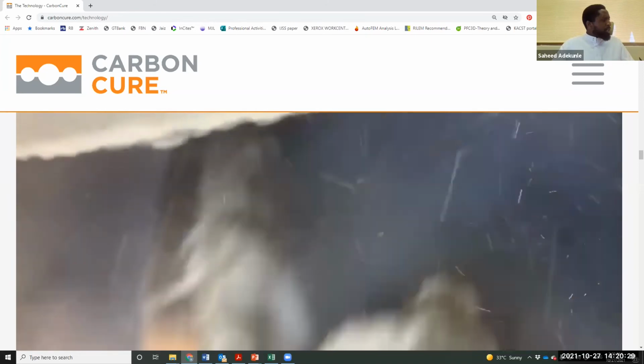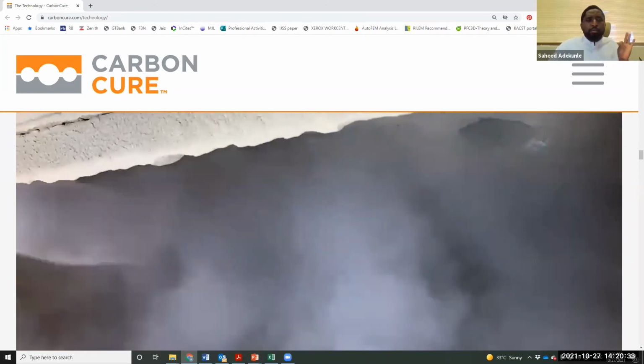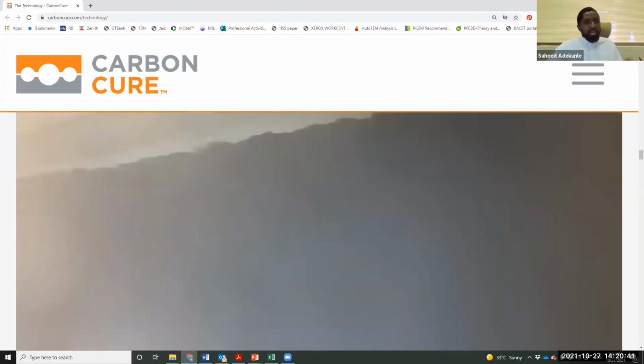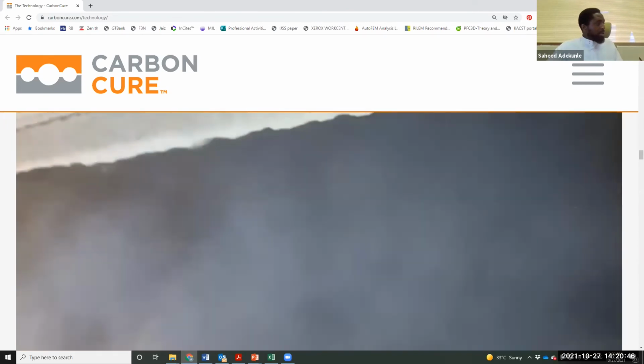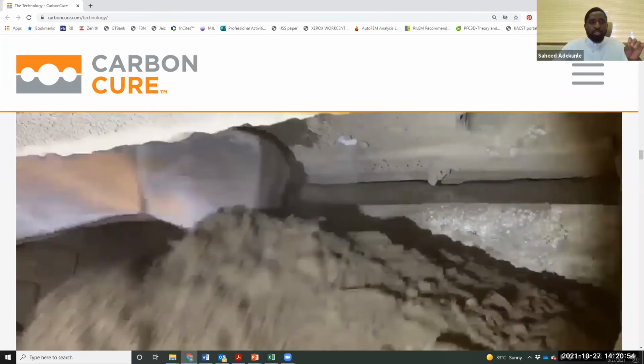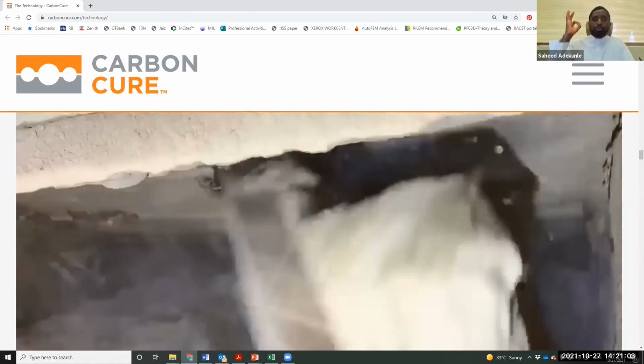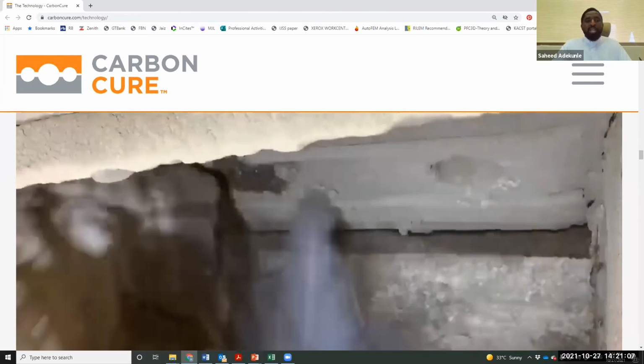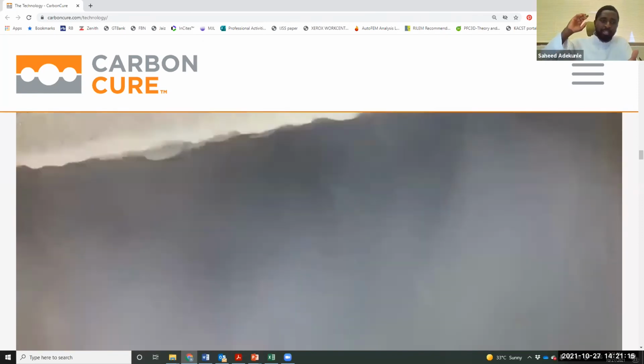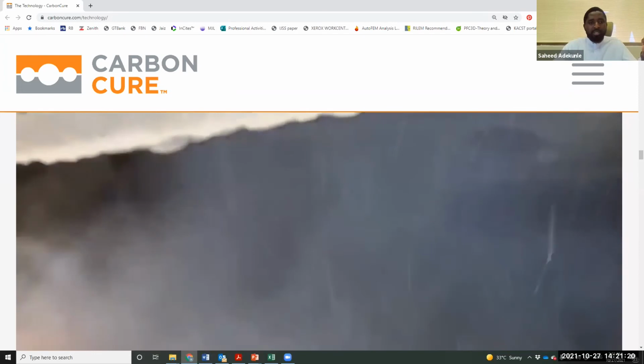Yeah, thank you so much for that question, because again, I'm showing on the screen the technology of CO2 admixing. This is a controlled dosage. As you can see, CO2 is pumped at atmospheric pressure. It's not under pressure. And by the way, in this technology, what you are seeing pumped here is raw captured emission. It's CO2 which has been partially purified from power plant capture. But this injection process is highly controlled in such a way that we don't allow 100% carbonation. If you allow 100% carbonation, as I showed earlier on, all the alite and the belite minerals in cement will be converted into carbonate, and there'll be no room for further hydration.